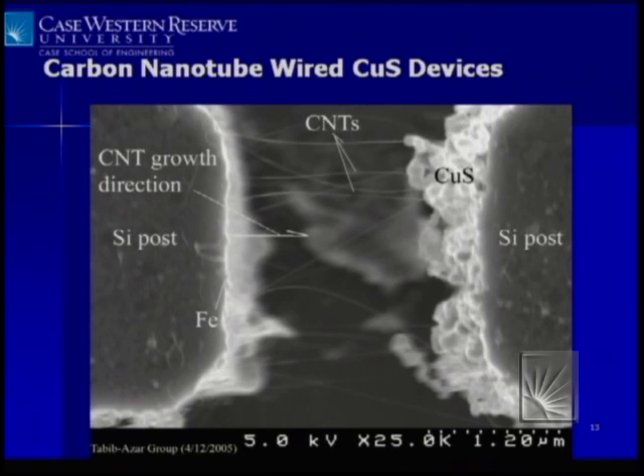This kind of shows up front. So copper sulfide cannot be taken up to 700 degrees centigrade or so. So what we did was we grew carbon nanotube between these two walls. This wall was covered originally with copper, and then after we grew the carbon nanotubes, we took it out and sulfidized the copper. And if you look at some of the carbon nanotubes, they kind of start sagging, because when you take copper and convert to copper sulfide, the volume increases by a factor of 2. And because of that, the carbon nanotubes are not stretched anymore. They kind of start sagging.